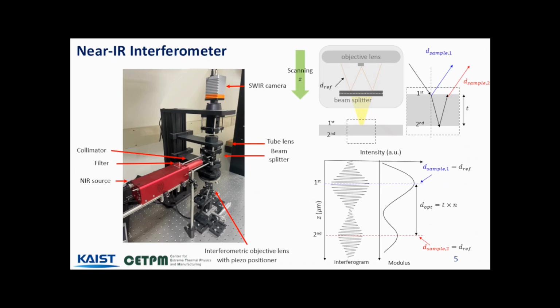So, as shown in the image, we developed a near-infrared interferometer. The setup is similar to a light microscope, and we use an interferometric objective lens with a piezo positioner to obtain scanned interferograms. During scanning, all the light reflected from the interfaces within the numerical aperture is collected by the interferometric objective lens. When the optical path difference between the reference and sample beams is smaller than the coherence length,